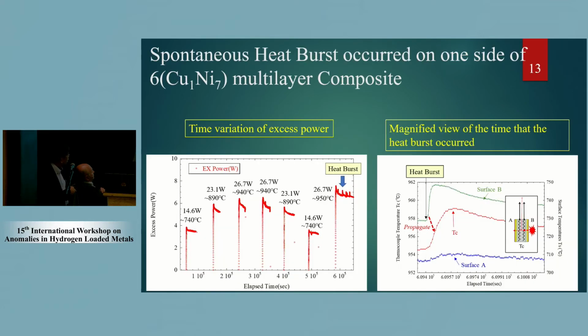Okay, so I would like to mention the heat burst phenomenon. Sometimes we observe a spontaneous heat burst like this. This is example data of the excess power versus time. At 950 degrees centigrade, we have many heat bursts here, and also here we have a heat burst. For this heat burst, we have a magnified view of the time that the heat burst occurred. We can check it closely like this.